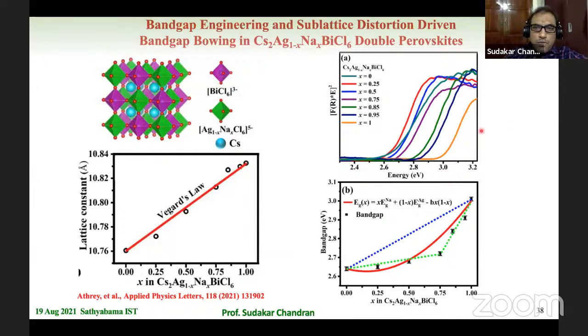We found one of the very interesting observations in this particular double perovskite structure. The double perovskite is something similar to single perovskite. The only thing is, there are two different cations, like in this case, silver and bismuth, and they order in an ordered fashion, in an alternate way. Therefore, the perovskite unit cell becomes almost double. In this particular case, we substituted sodium in place of silver, and the structural changes are as usual. It's a very linear change, so there is nothing unusual.